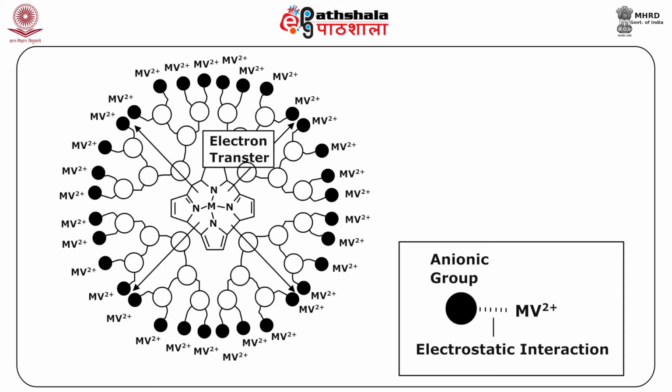You can see the electron transfer via a dendrimer core. Electron transfer is induced by the photoexcitation of the central porphyrin to the adsorbed methyl viologens. The size of the dendrimer also affects the transfer of an electron. As the size of the dendrimer tends to increase, electron back transfer gets effectively suppressed and a long-lived electron separation state is achieved.